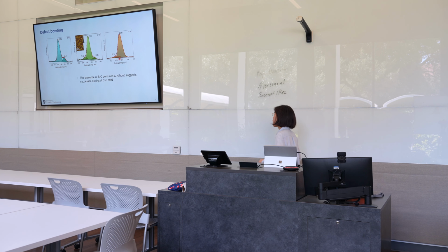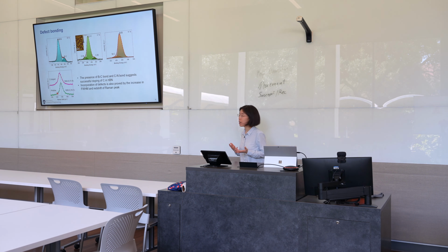Now, if you look at the chemical bonding environment of these carbon defects, you can see from the XPS spectrum that the carbon is bonded with both boron and nitrogen. And if you look at the Raman spectrum, you can see the Raman modes of boron nitride are slightly redshifted and widened compared to the pristine sample. So these are all proofs that carbon has been effectively integrated in the boron nitride lattice.